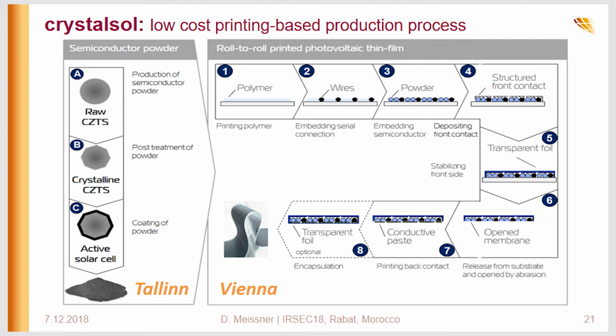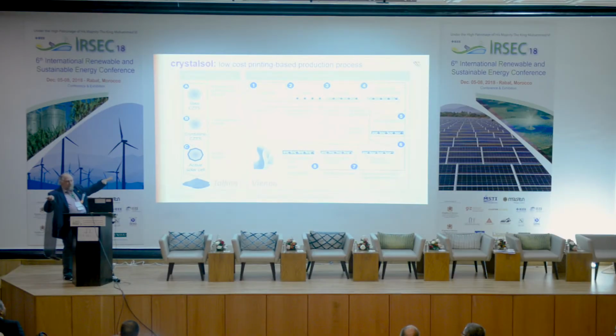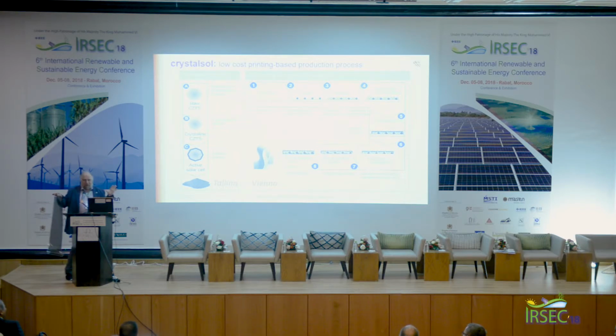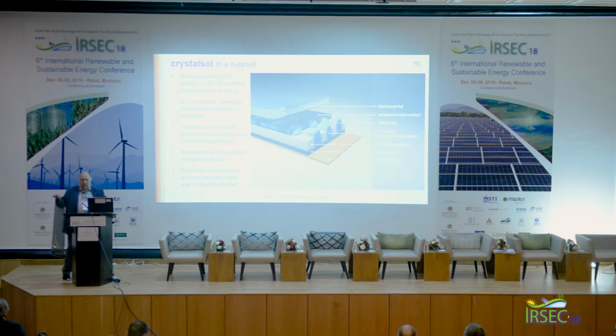We print a plastic film or a polymer film on any substrate, because the substrate is afterwards removed. We put wires into it to make the series connection. We put the powder in. We make the front contact, also by printing, transparent, as you can see here. Then we seal the front side. We remove everything from the substrate so that we have access to the back side. We polish the back side mechanically. We open the grains, basically, and we print the back contact on the back side and seal the back side. That's how we make these modules, and this is how they look like.